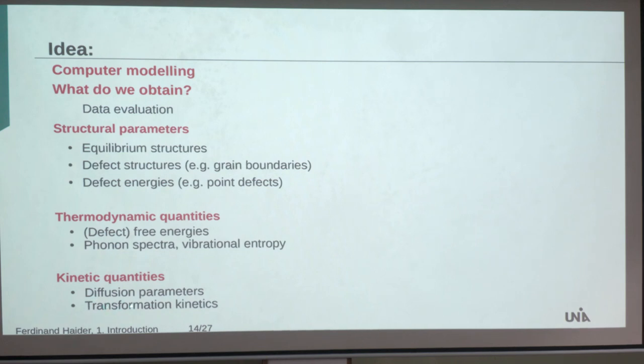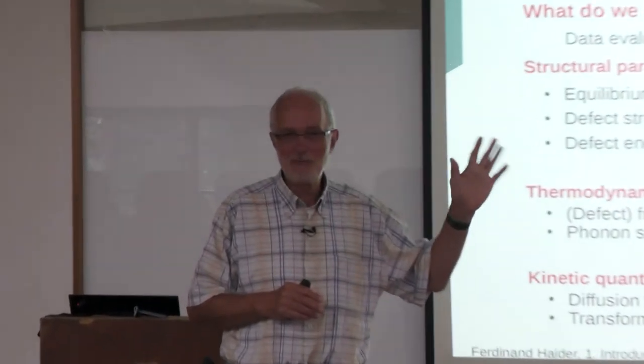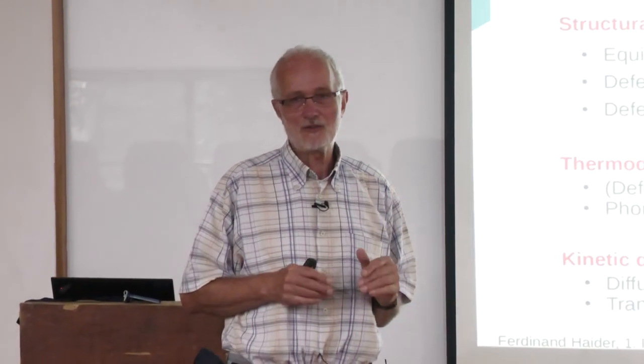And where we come to the limits of MD, but where the power of MC comes in, transformation kinetics. In molecular dynamics, we are restricted in time. I come to this in more detail later on. Typically, you can run simulations for days or weeks. They describe times of nanoseconds and microseconds at most. So only very fast phase transformations can be described using MD. For example, martensitic transformations, this is something which occurs with the velocity of sound. This is feasible, but these unmixing reactions I showed in this simple MC model, you cannot describe in MD.